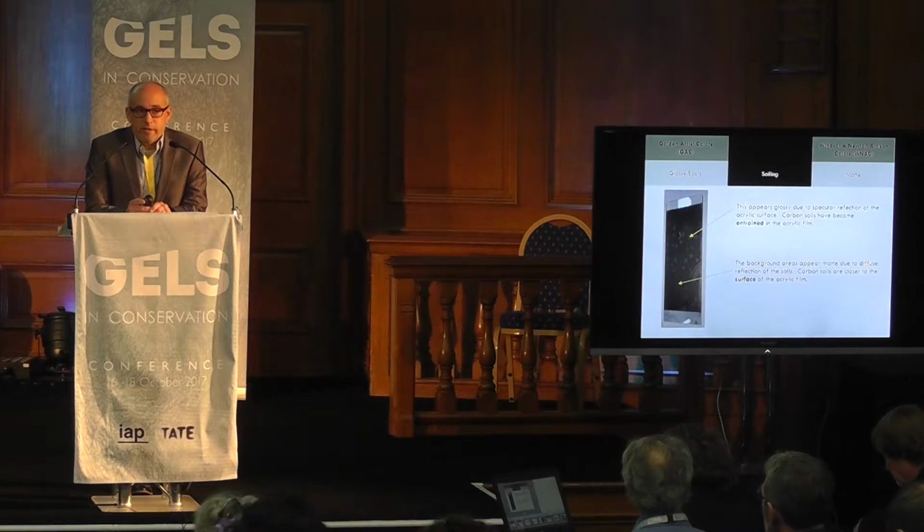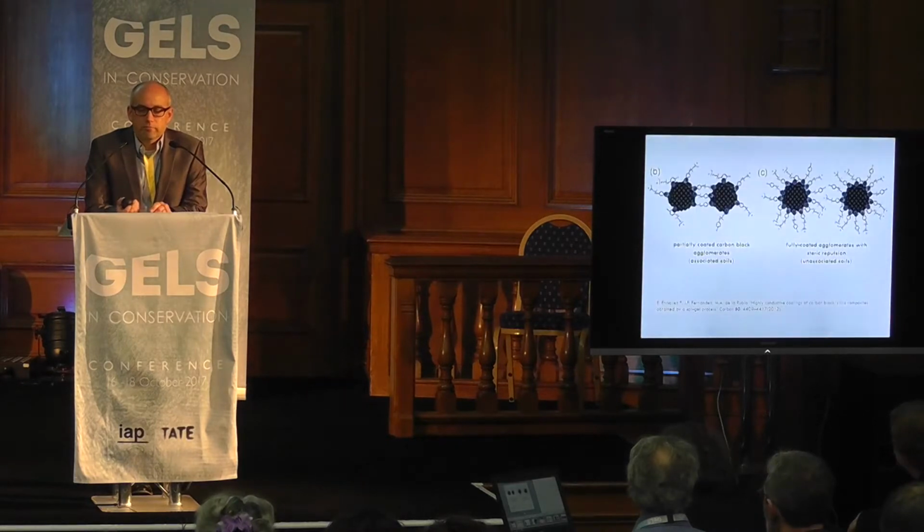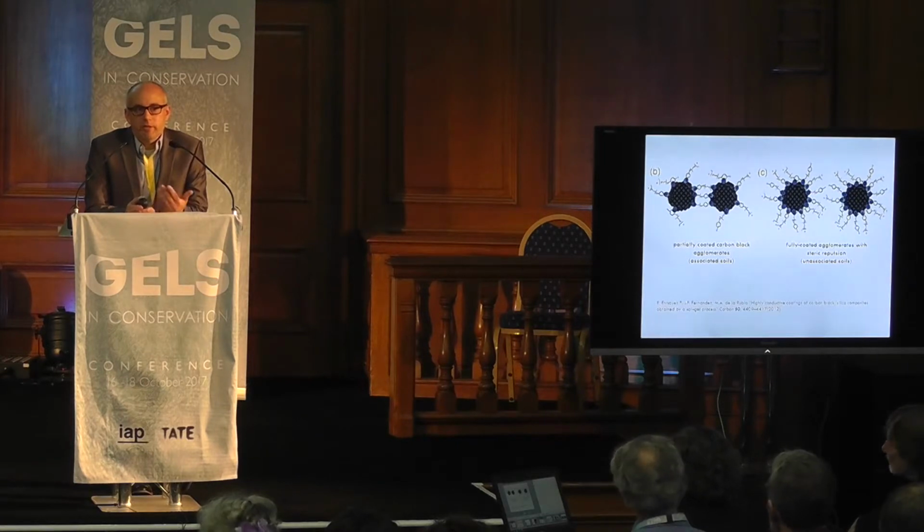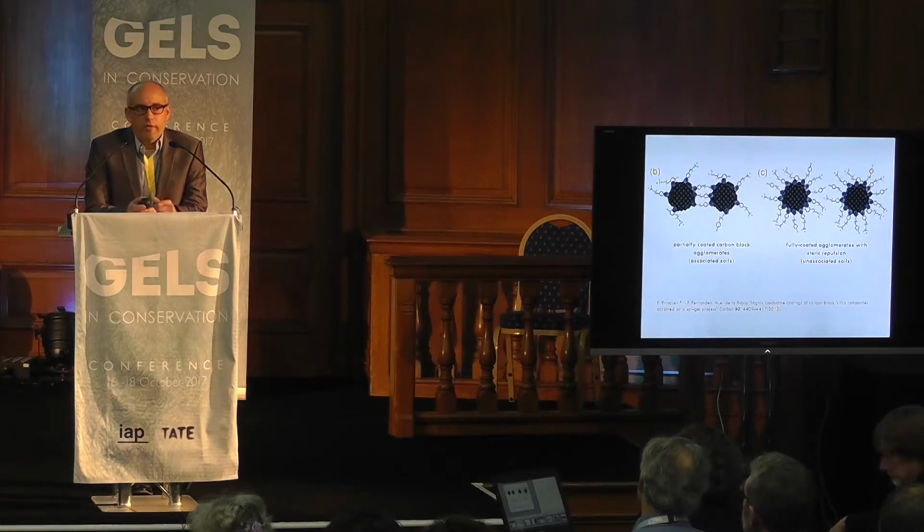We didn't notice this when cycling temperature and relative humidity with the Winsor and Newton Artisan colors. We didn't see these spots appear. The reason we came up with for why these spots appear is associated soils. We know that cycling temperature and relative humidity is going to bring surfactant into the paint film, dragging with it particles that are associated at the surface.